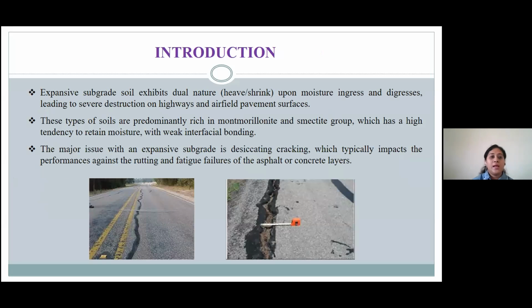As we all know, the dual nature of the expansive soil exhibits low volumetric stability upon moisture imbalance, leading to extensive destruction of the structures. Now, periodic variability in the swell shrinkage activity is predominantly constituted of the montmorillonite and the smectite clay, which has a high affinity towards water. And the leading worldwide issue with expansive soil is basically desiccation cracking, which usually alters the long-term sealing effects, and it causes damages on various civil engineering structures.